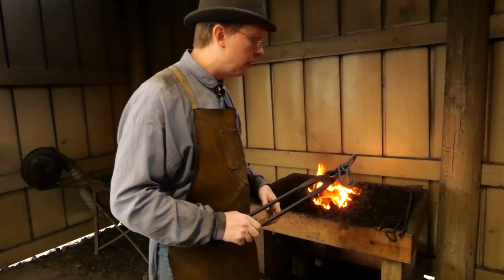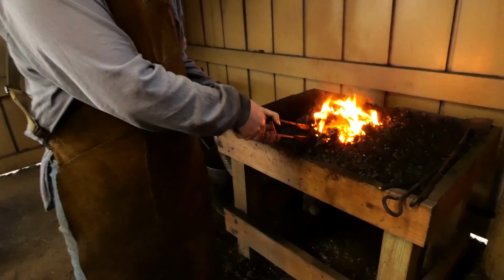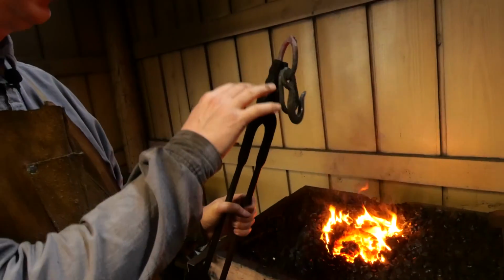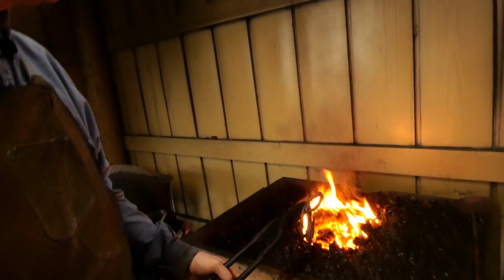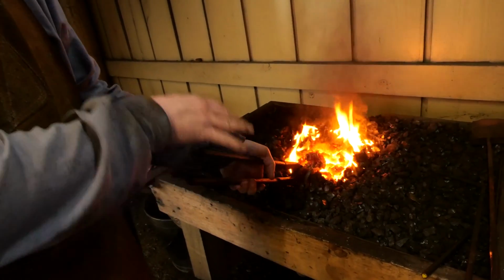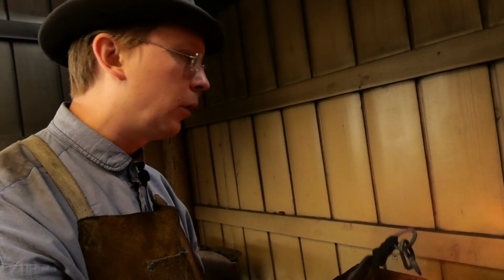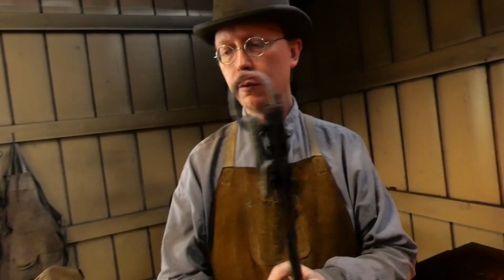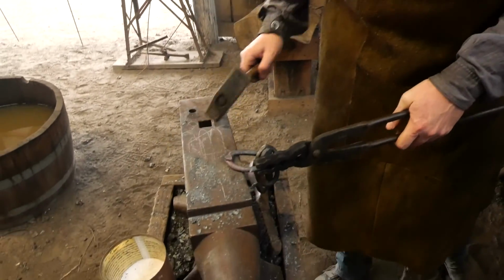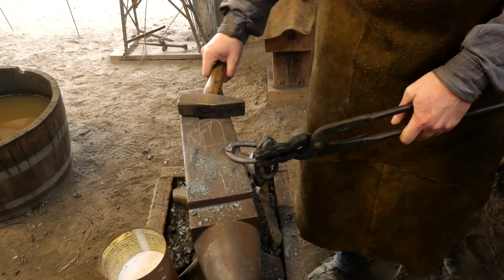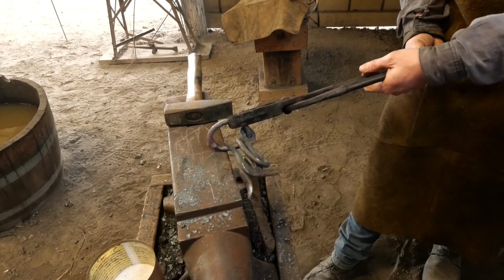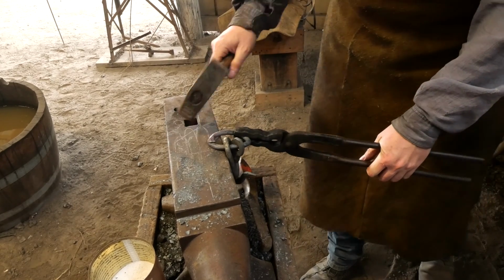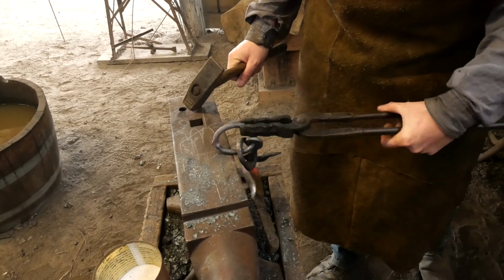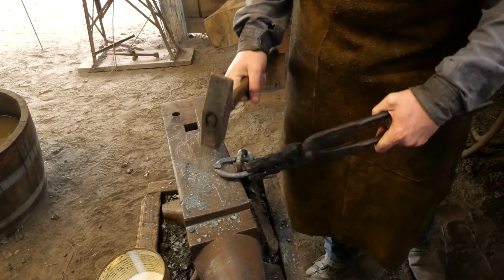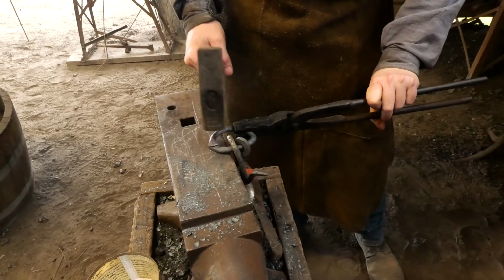So we're going to make sure that we've got both our link and our hook hanging off the back end into the fire with just the welded piece in the hottest part of the fire. Once that's up to welding temperature, we're going to pull it out over to the anvil, couple hammer blows, and then we're going to make sure to flip it in this direction and a couple hammer blows.